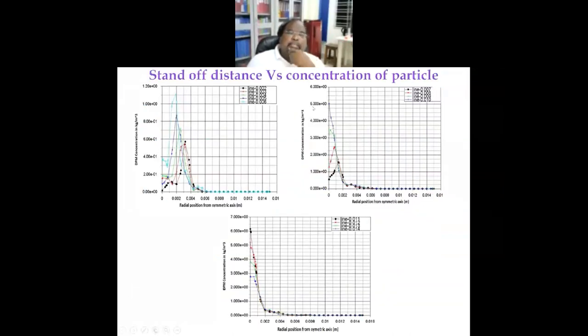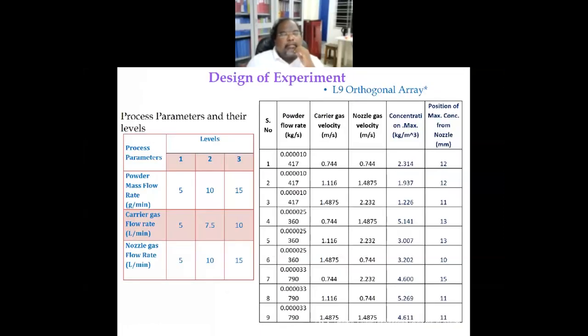And from the standoff distance and concentration of particles, we basically tried to get the design standoff distance, that is, what should be the standoff distance between the nozzle and the substrate. Then by this simulation, we tried to get some primary value, and tentatively we came very close to 1 millimeter. And then we did some design of experiment here. It's just a very crude level of design of experiment to get some kind of value, using a very old method that we used at that time.